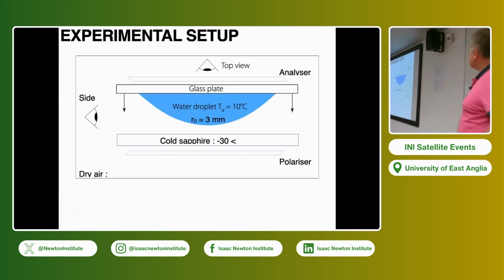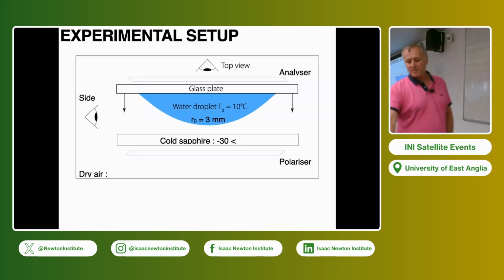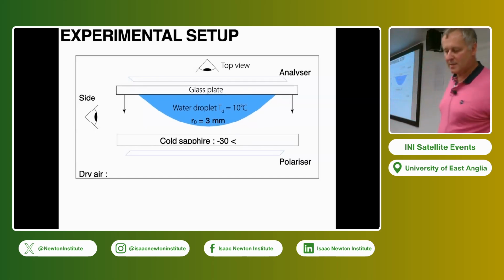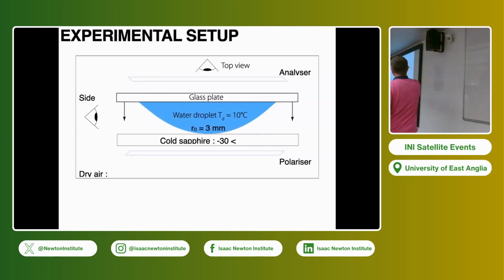Okay, so here is the experiment that we have done. We take a water droplet. We do all the experiments with water, at a given temperature, and we put it on a glass plate, and we will make this drop slowly contact a cold sapphire. This sapphire is at minus 30 degrees, to minus 20, whatever the temperature. And then we will look at the spreading.